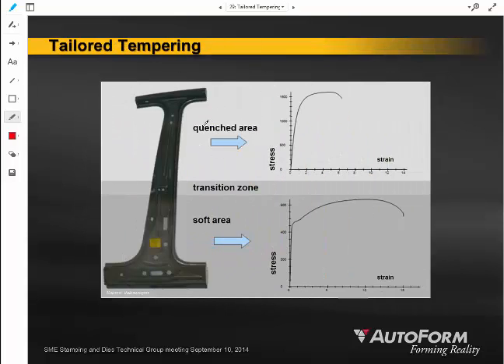So in this case, the B-pillar, they quenched the B-pillar at the top. That's going to form a lot of that martensite microstructure. That's going to be the strongest, highest strength material that this B-pillar is ever going to see. Then there's going to be a little bit of a transition zone to the material that is allowed to cool